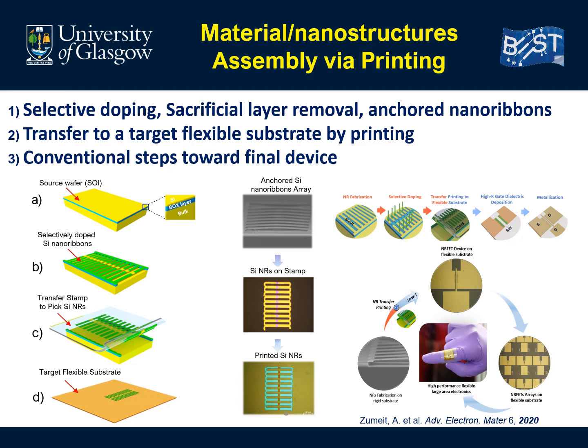A major challenge here with the nanostructure-based devices is that some of the critical fabrication steps, for instance, the nanostructure fabrication and doping, and the high-K dielectric, require a high temperature that is incompatible with the flexible substrate. Therefore, it's important to develop and optimize device fabrication strategies such that all the fabrication steps are carried out at low temperatures.